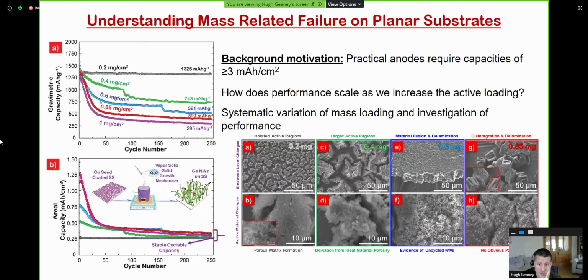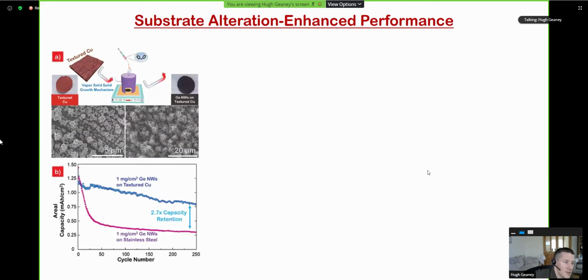And in terms of the micron level active material then, we couldn't see any obvious porosity in the active material. So this led us on then to the use of a different current collector to see, could we get around those issues. I mean, a lot of the issues as we went to the higher loadings previously, you see, were due to disconnection with the current collector.